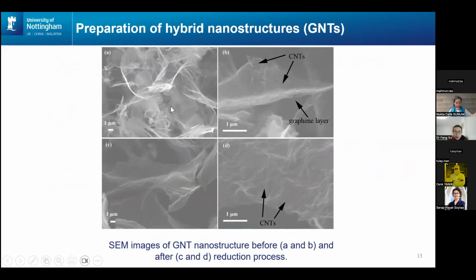If we look at A and B, we can see very thin layers of graphene oxide, and on the surface there are carbon nanotubes attached because of the pi-pi interaction. But because of the attached carbon nanotube on the surface, the graphene restacking didn't happen because the carbon nanotubes stopped them and worked as a very effective spacer.